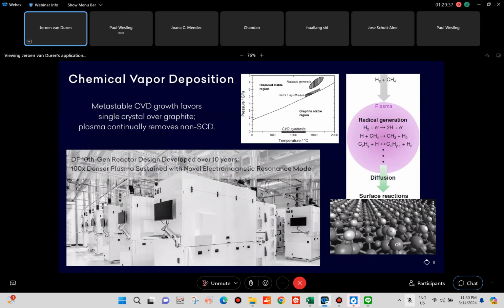Quickly, a little bit on the growth. If you look in the middle, you see a temperature versus pressure phase diagram for carbon, and what you can see is that the CVD synthesis conditions are low pressure and around 1,000 Celsius, which is actually where graphite is more stable than diamond. So the growth conditions are such that the diamond needs to be favored over the graphite. Hydrogen plays a big role in that, and your reactor design and the plasma conditions play a big role in that. We're currently in our 10th generation of our reactors that have been developed over the past 10 years. And as I mentioned, 100 times denser plasma that is sustained continuously with a novel electromagnetic resonance mode.